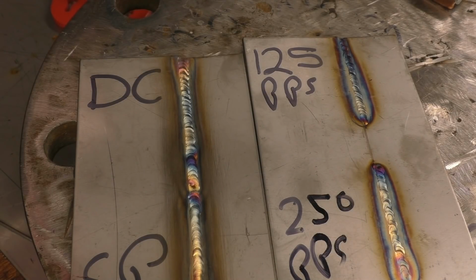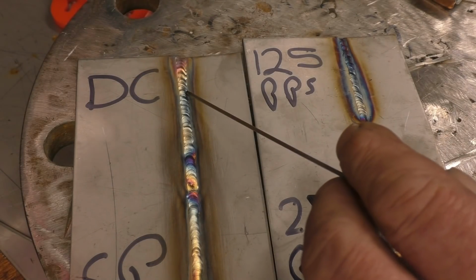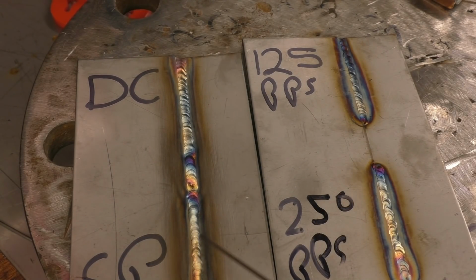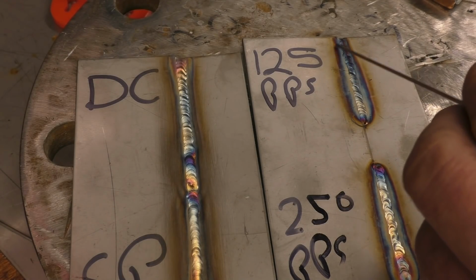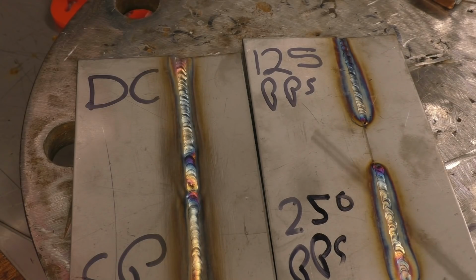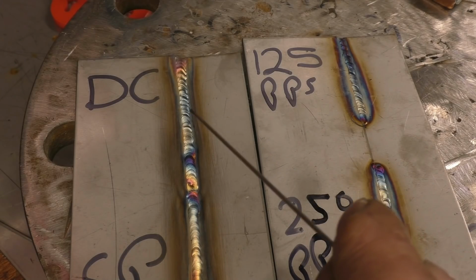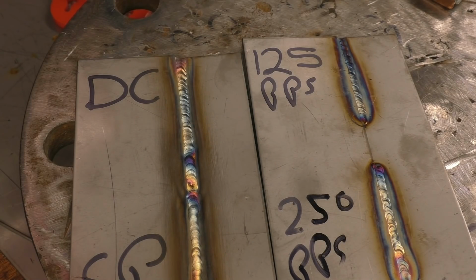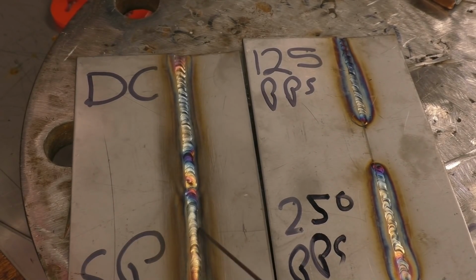Right, there are the 4 welds. That one there, straight DC. That was a slow pulse, 125 pulses a second, and 250. On these two you can see that the heat affected zone on the 125 is wider than on the 250. The 250 is a much tighter, finer arc. That's the one I prefer to weld on. It's tighter than the DC. The pulse is not ideal for this particular job.